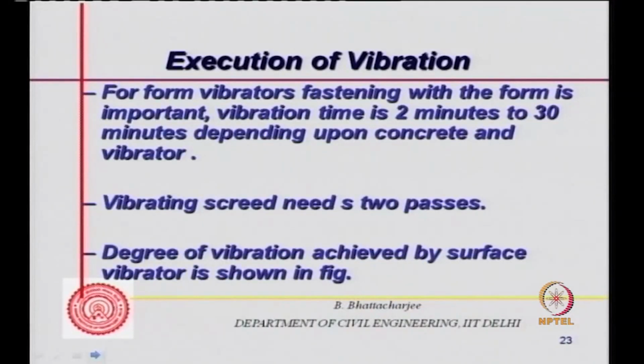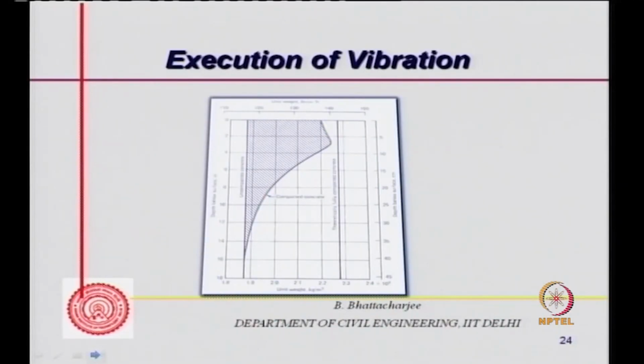And the degree of vibration achieved by a surface vibrator, of course, one can see from the figure that is there. Actually, vibration is only up to a certain depth, about 8-10 centimeters from the top, which means 80 mm, and not really much. After that, the density reduces down. So only the top portion is maximum that you can actually vibrate. Similarly, a shutter vibrator also will not go throughout the section if the section is thick. So that's what it is.